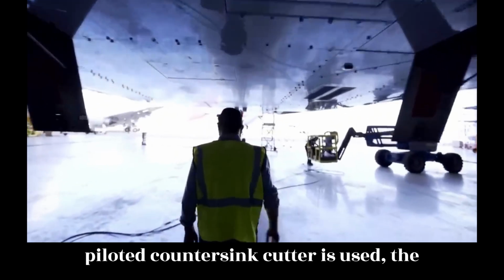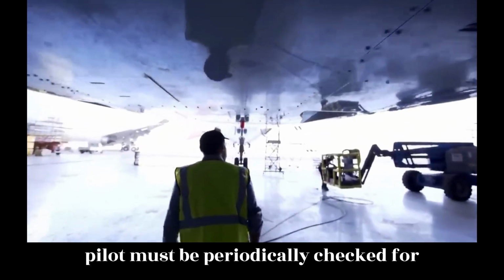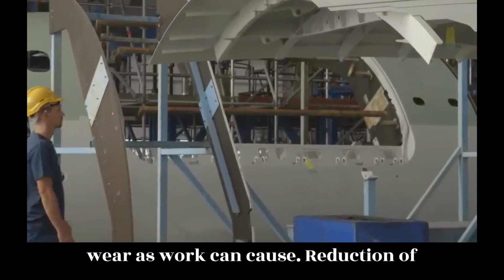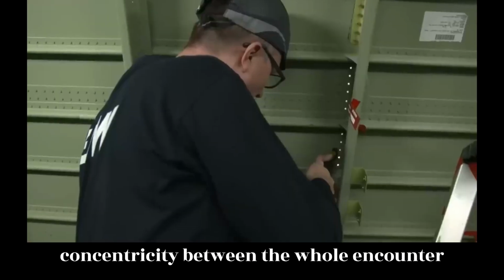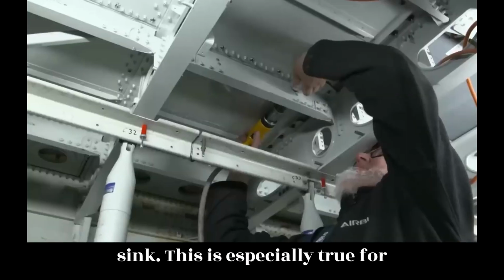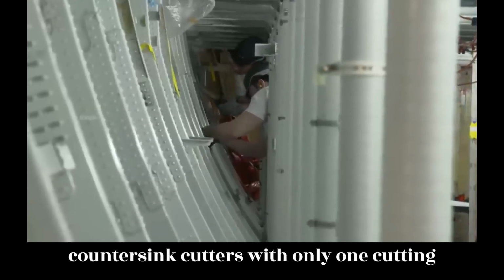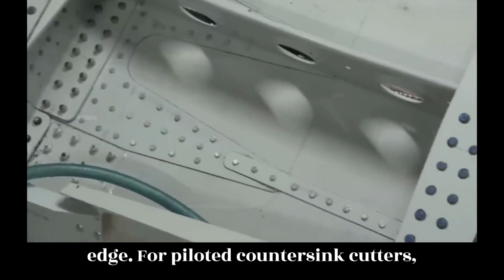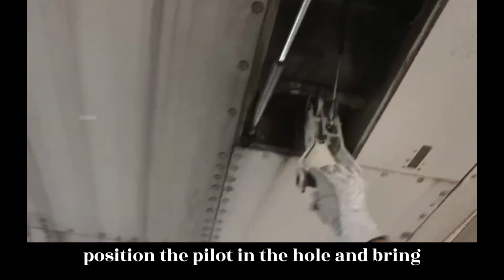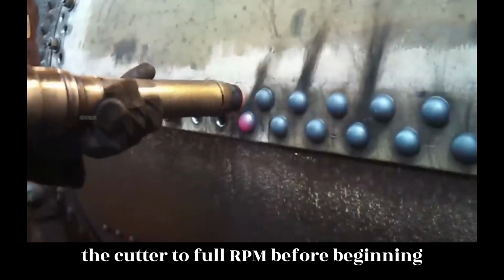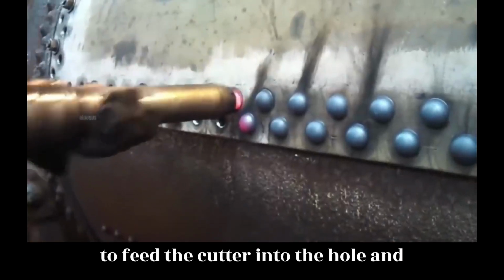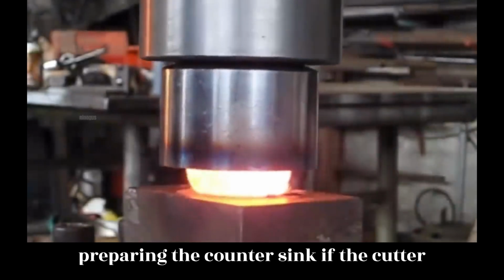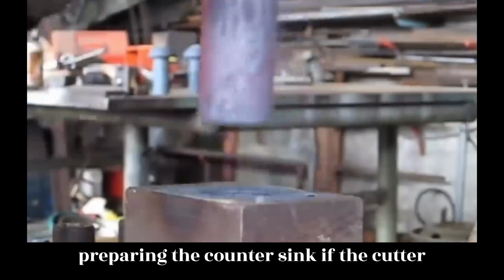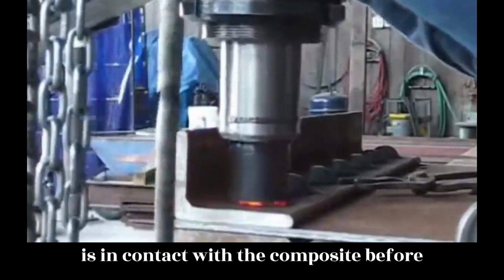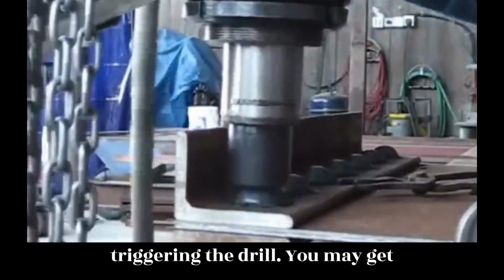When a piloted countersink cutter is used, the pilot must be periodically checked for wear, as wear can cause reduction of concentricity between the hole and countersink. This is especially true for countersink cutters with only one cutting edge. For piloted countersink cutters, position the pilot in the hole and bring the cutter to full RPM before beginning to feed the cutter into the hole and preparing the countersink. If the cutter is in contact with the composite before triggering the drill motor, you may get splintering.